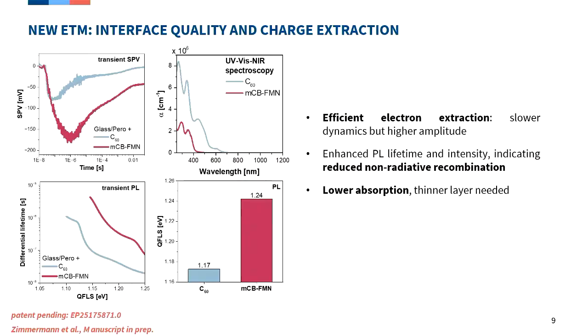So on this figure, the so-called SPV - surface photovoltage - is a dedicated measurement developed by colleagues in our center. You hit your sample with a laser pulse or illumination, and then you can track how charges separate and build up a voltage, which is what you see here.